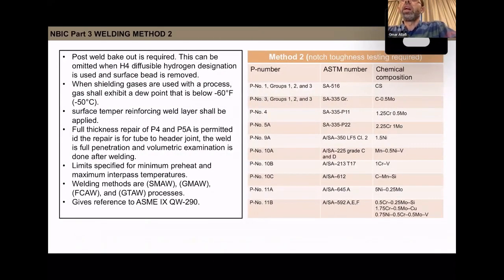For NBIC Part 3, we have 7 methods. Methods 2 through 5 are for temper bead, and the last 2 methods are for controlled deposition. In each method, I listed all the materials permitted and the chemical composition of these materials. In weld method number 2, this is when impact testing is specified. So they have an additional requirement for shielding gases. This is the moisture requirement in QW-290.4, which is a non-essential variable, but they're making it essential here.